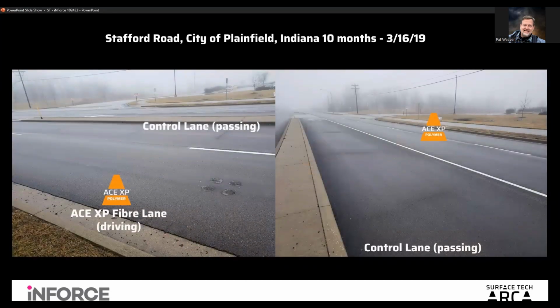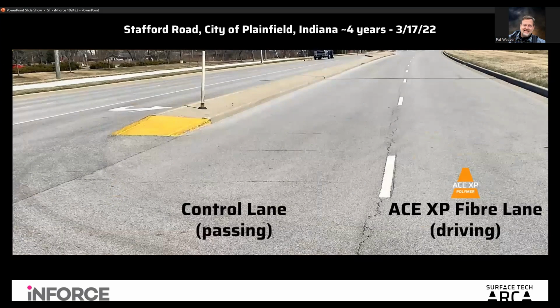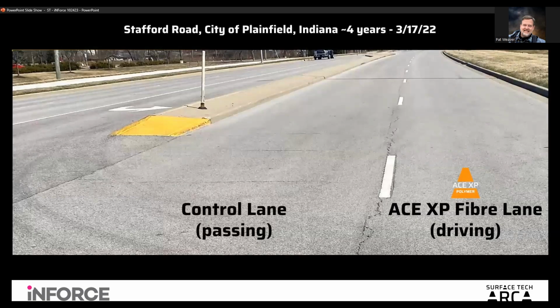This is what I'm talking about, the enhancement into a polymer mix. Again, this is about a year later, starting to see the cracking reflect through even more. This is cracks measured by Mr. Blankenship. In 22, 4 years in, you can see the cracks coming across. They hit our section and stop abruptly, and they don't pass through, which is a rarity.